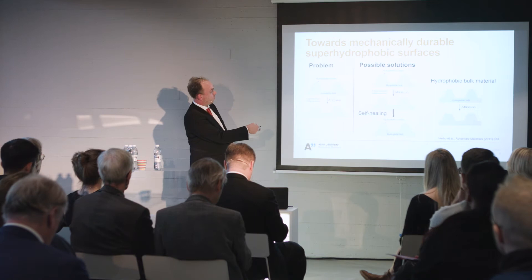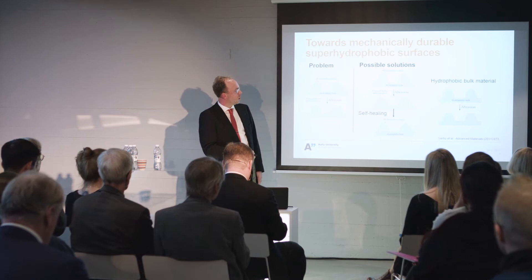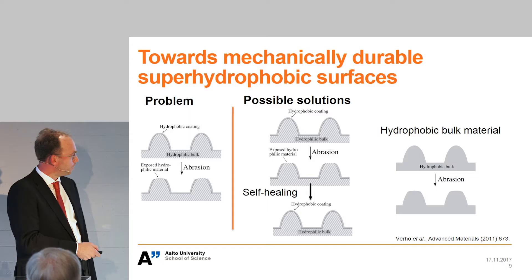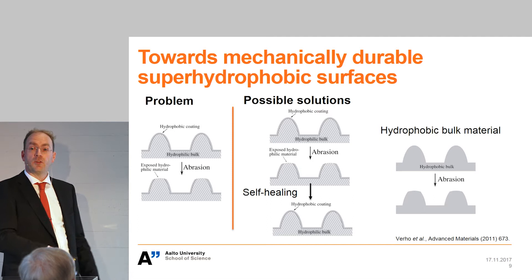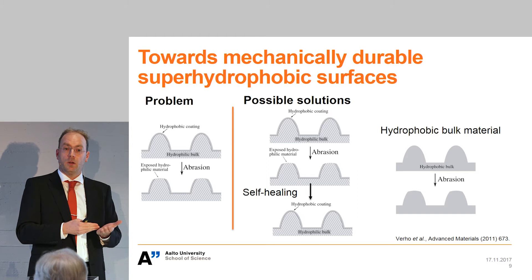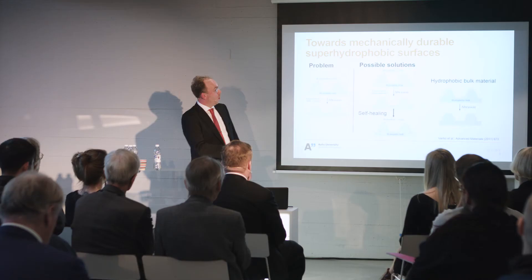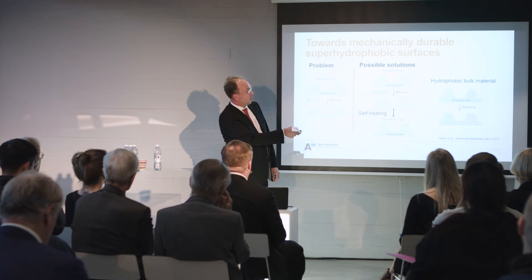People are working on solutions, and our group has contributed. One problem is that when you create surface roughness and add a hydrophobic coating, damaging it exposes hydrophilic areas that water sticks to. There are different kinds of solutions. One is self-healing: some surfaces can spontaneously recover their wetting properties after damage, similar to how a cut in our skin heals in a few days. Another solution is to start completely from a hydrophobic bulk material, so there are no hydrophilic pinning sites.